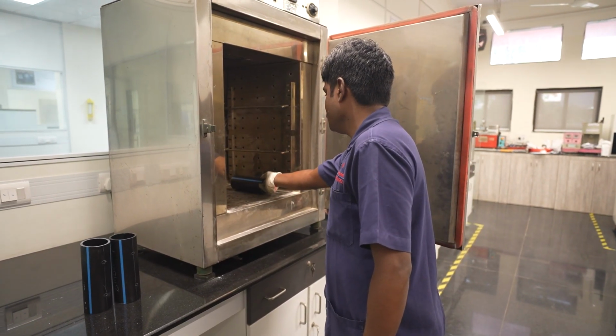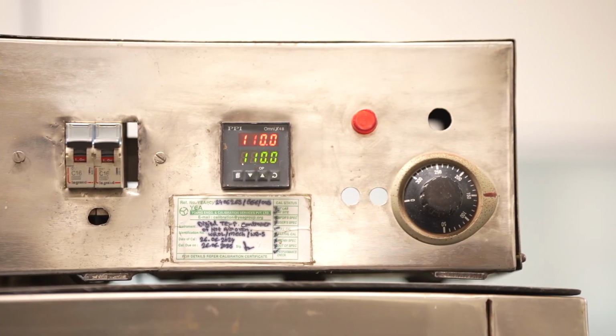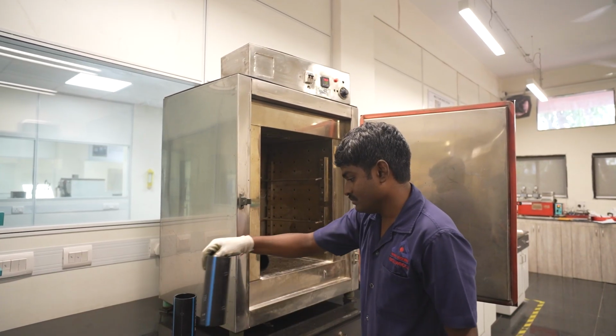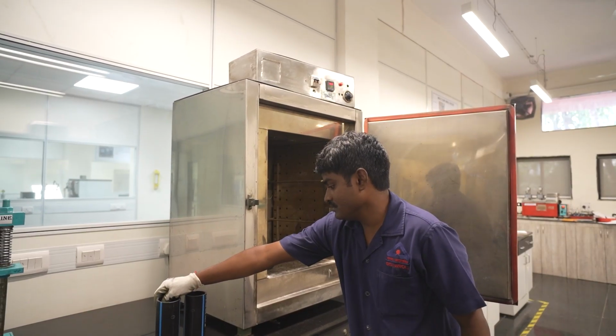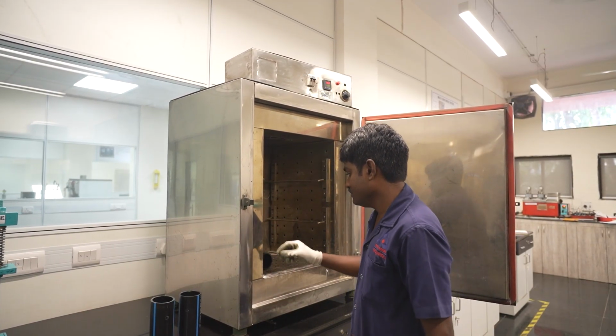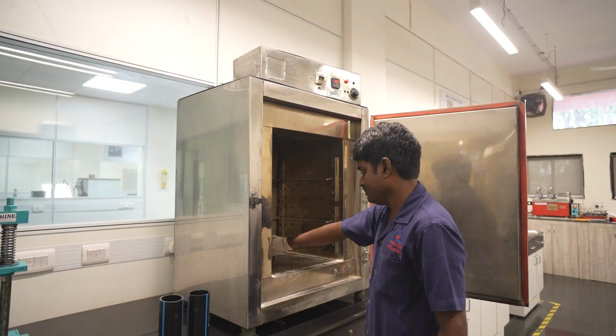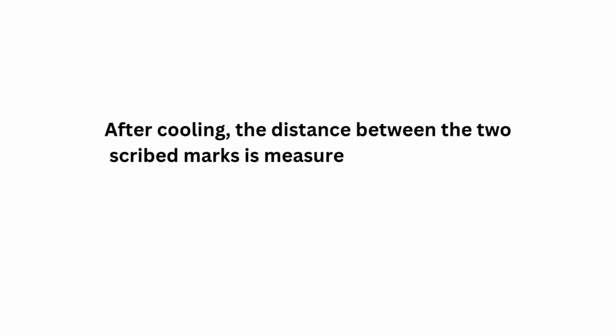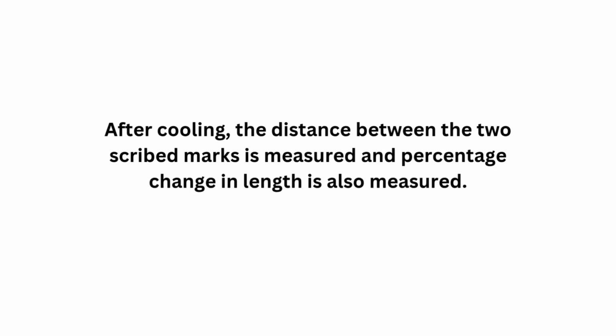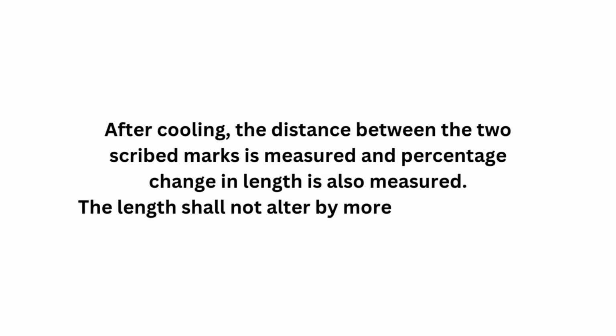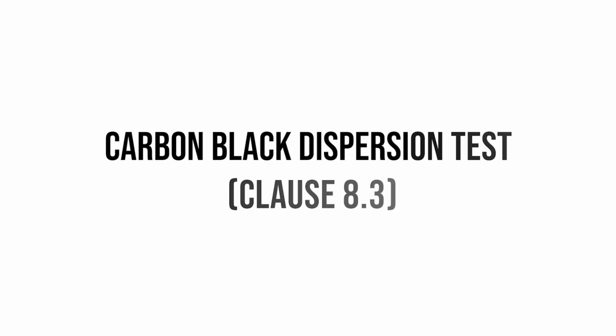Specimens are heated in an oven at 110 ±2 degrees Celsius with continuous forced air circulation and then allowed to cool to room temperature. After cooling, the distance between the 2 scribed marks is measured and the percentage change in length is also measured. The length shall not alter by more than 3%. The next test is the carbon black dispersion test, which evaluates the uniform distribution of carbon black within HDPE pipes.